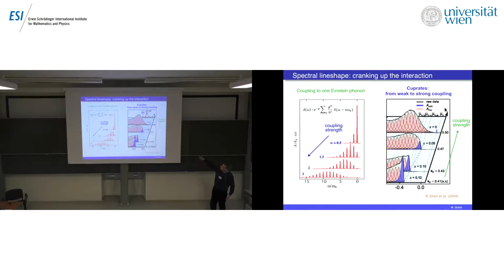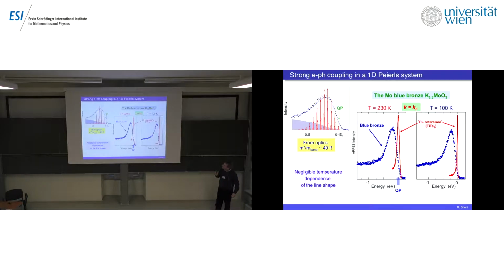And this is pretty much what is observed in this series of cuprates as a function of doping. And people believe that indeed by going towards more and more underdoped cuprates, the coupling becomes stronger and stronger with the phonons. Now, this is another example from our own work a long time ago for a 1D Peierls system, the molybdenum bronze, a molybdenum oxide, potassium doped. The spectrum looks rather bizarre. It's a broad spectrum, and well, you might think that the peak energy corresponds to the energy of the quasi-particle, but actually this is inconsistent with many results.